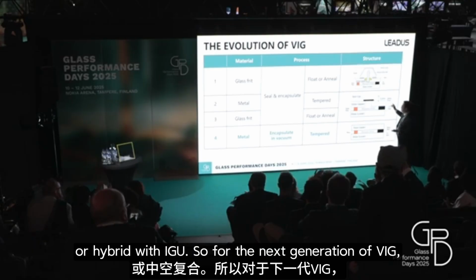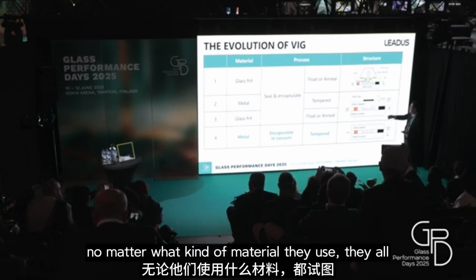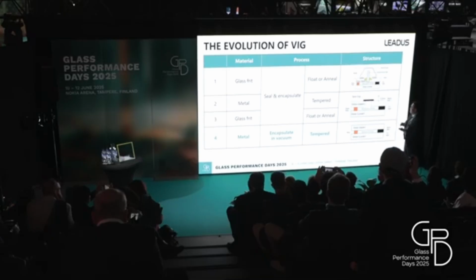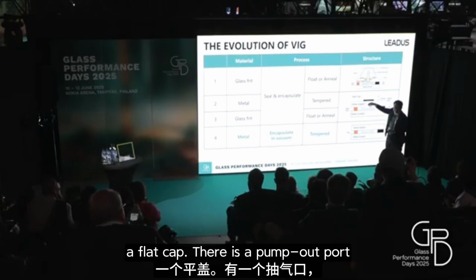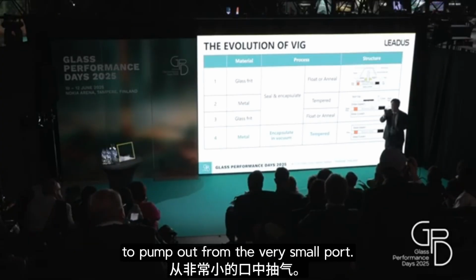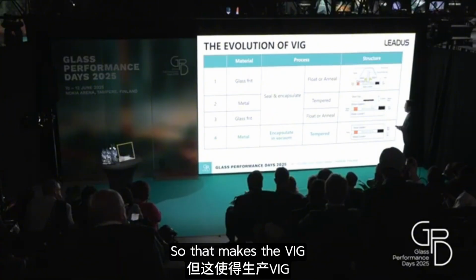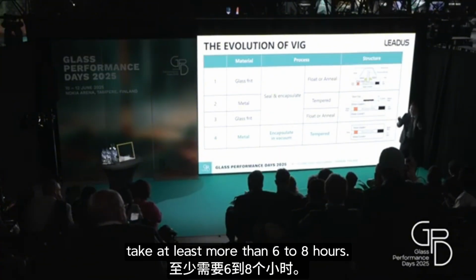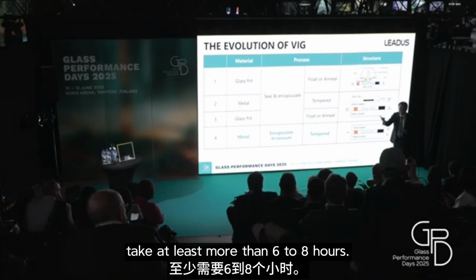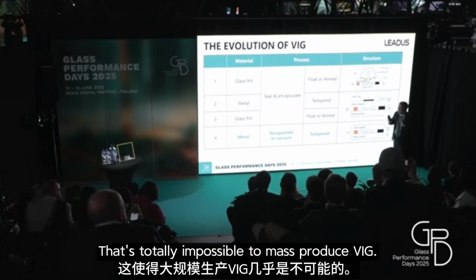So for the next generation of VIG, no matter what kind of material they use, they all develop to a flat cap, with a pump-out port to pump out from the very small port. So that makes VIG take at least more than 6 to 8 hours. So that's totally impossible to mass produce VIG.